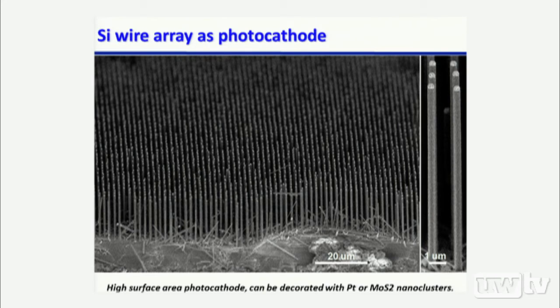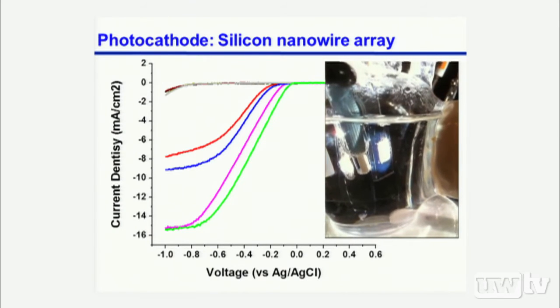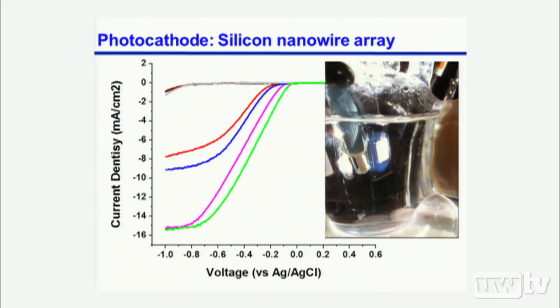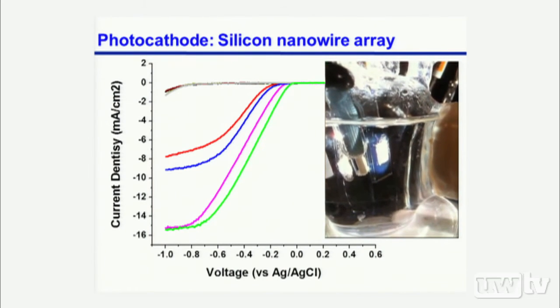Typically, with these silicon nanowires, if you engineer the interface, you can reasonably extract a photovoltage of up to 400 millivolts or slightly above, and the current density can be around 20 milliamps per square centimeter as a photocathode. So we do have some good photocathode material. Now, if you replace silicon with our more recent indium phosphide nanowire array, the current density can go up to 30 milliamps per square centimeter. Photovoltage can go up to 700 millivolts. So that's pretty decent from the photocathode end.